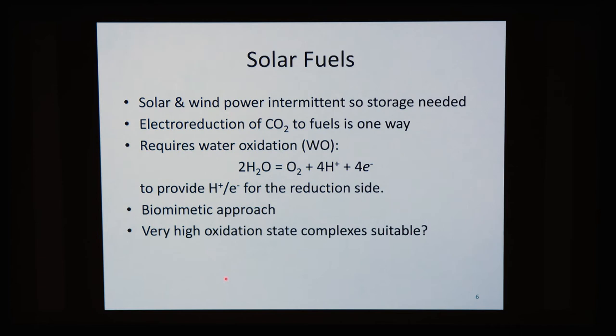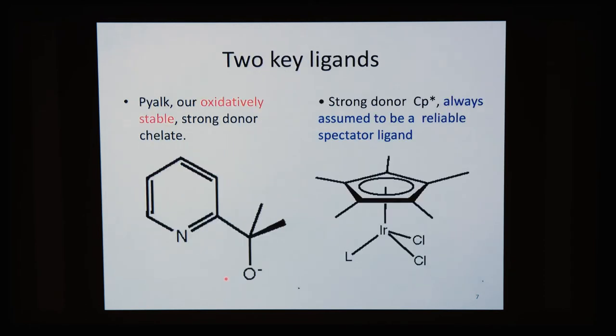And what we need are some very high oxidation state complexes, and ones which have ligands that are very, very oxidation resistant. So two key ligands involved here are pyalk, which is our oxidatively stable strong donor chelate, which is going to help us achieve these high oxidation states, and a very strong donor Cp star, which is always assumed to be a reliable spectator ligand, but here it isn't.